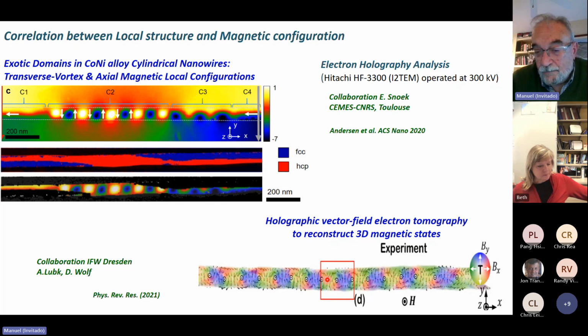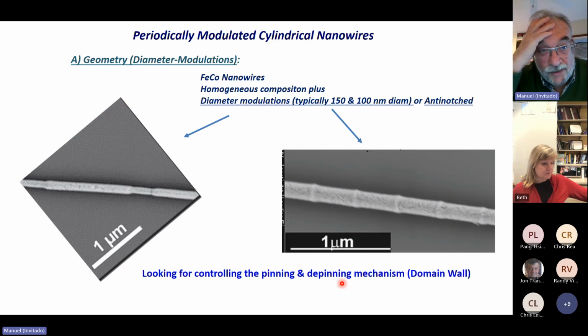We have also the same structure as these exotic domains I mentioned before. So we can have a very complex domain structure in these nanowires, depending, of course, on the crystalline structure and composition. Let me go now to the modulation in diameter. As you see here, two images of these individual nanowires with alternative segments with different thickness. I will be talking only on the first one.